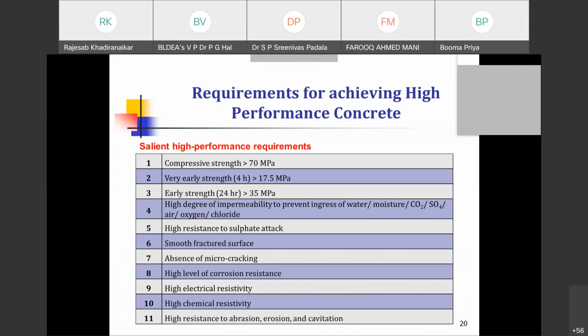So in addition to these permeation characteristics, there can be other performance characteristics which may become the specific need for high performance concrete. The other salient high performance requirements, in addition to the permeation characteristics, are a compressive strength of more than 70 MPa. It is already defined. Very early strength, within 4 hours, 17.5 MPa for highway constructions particularly. Then early strength more than 35 MPa.